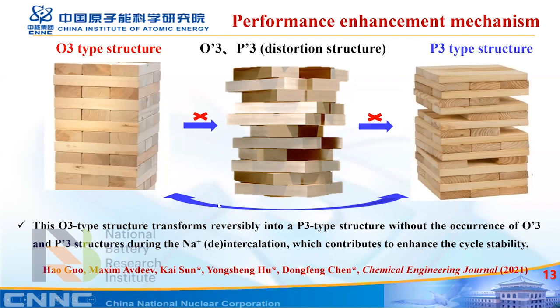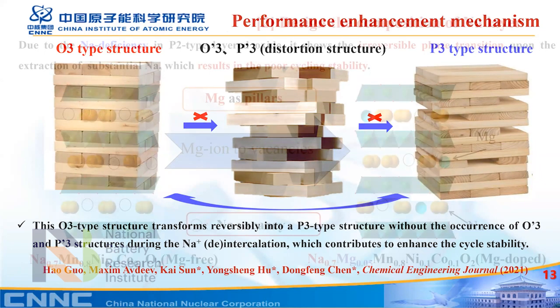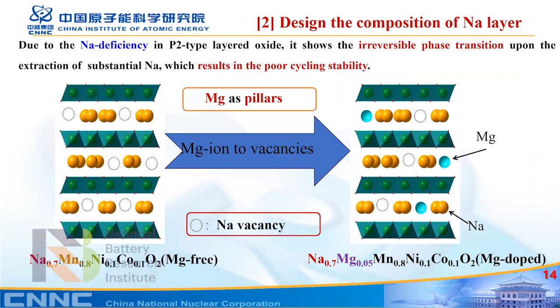Secondly, we designed the sodium layer. That's our second work. Here we use another kind of structure, the so-called P2 type structure oxide, to design the sodium layer. It is well known that prismatic P2-type layered oxides are typically sodium deficient. That means sodium ions are not saturated in the structure. As shown in the figure, this system has several intrinsic sodium vacancies in the crystal structure. Therefore, we could think about doping some other element into those sodium vacancies to improve the performance of the battery.